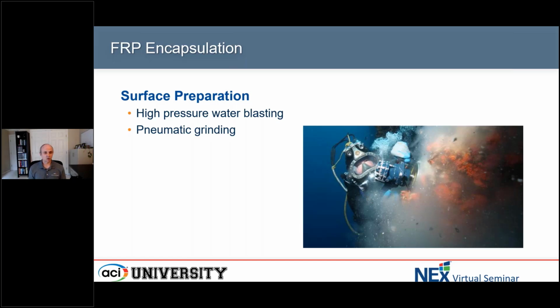Now, one thing to note about underwater structures is that it is often very critical that you do surface prep very close to the same time that you're doing other final repair applications. A lot of times the prep that you do to prepare the surface only lasts for a matter of maybe 24, 48 hours before there's new marine growth or there's new surface rust on the structure. So oftentimes there's very tight windows between actually prepping the surface and then executing the ultimate repair that's done. So in a lot of cases, you'll see specified windows between doing surface prep and then doing the actual repair application.